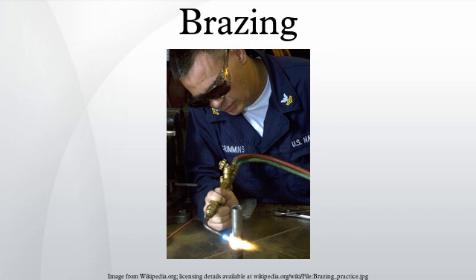In brazing copper, a reducing atmosphere may react with the oxygen residues in the metal, which are present as cuprous oxide inclusions, and cause hydrogen embrittlement. The hydrogen present in the flame or atmosphere at high temperature reacts with the oxide, yielding metallic copper and water vapor, steam. The steam bubbles exert high pressure in the metal structure, leading to cracks and joint porosity. Oxygen-free copper is not sensitive to this effect. However, the most readily available grades, for example electrolytic copper or high-conductivity copper, are. The embrittled joint may then fail catastrophically without any previous sign of deformation or deterioration.